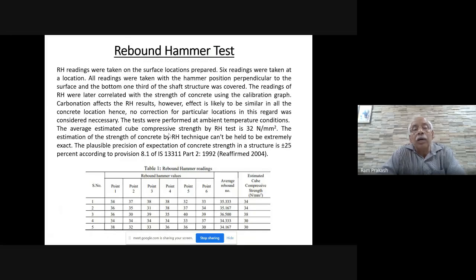These are the results of the rebound hammer test. RH readings were taken on the surface location prepared. 6 readings were taken at each location. All readings were taken with the hammer position perpendicular to the surface, and the bottom 1/3 of the shaft structure was covered. The readings of the RH were later correlated with the strength of the concrete using the calibration graph.